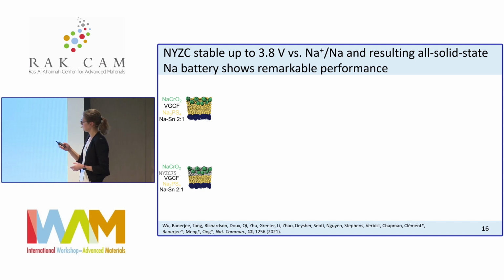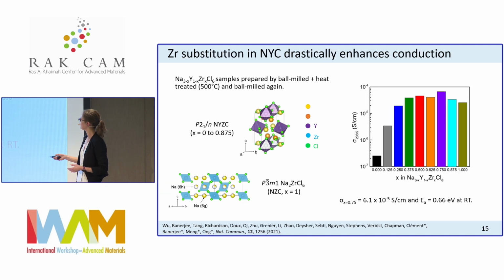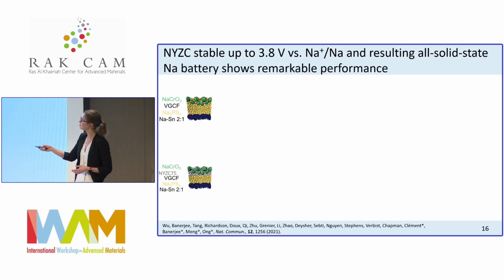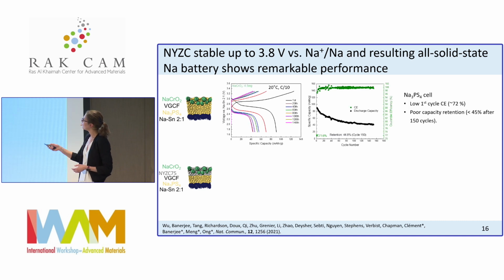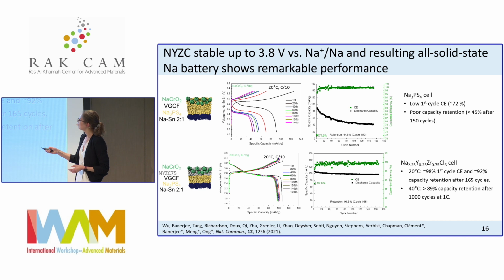And what you find if you make an all-solid-state battery with our catholyte NYZC75, which is basically this material here at 75% zirconium substitution, and if you compare this to the all-solid-state battery without this catholyte, without the catholyte you get initially good performance, but degradation of the performance quite quickly with cycling, whereas with the catholyte you get a much more stable performance. And even after 1,000 cycles, if you cycle this battery at 40 degrees Celsius, you get about 90% capacity retention, which is very impressive.